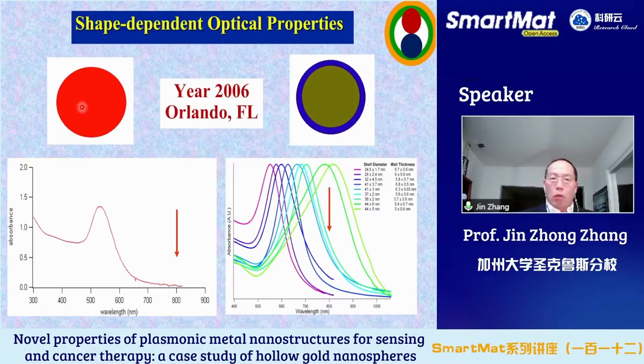But his talk is using solid gold like this. I noticed in his talk, he was using a laser at 800 nanometer, as I draw here. As you can see, this absorption or extinction at 800, that's a very little absorption. For photothermal ablation to work effectively, you need a lot of absorption, more heat. So therefore you want strong absorption, so you should shine your laser around 520. So I asked him, why do you use 800 instead of 520? He said for the near IR, this is called the near IR, 800 region, the light goes deeper into tissue. So the deeper penetration. So for biomedical detection and therapy, they prefer 800 nanometer.